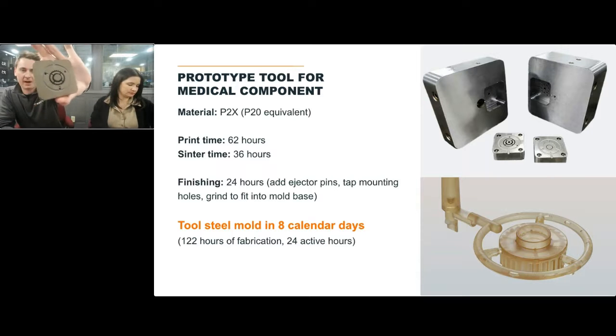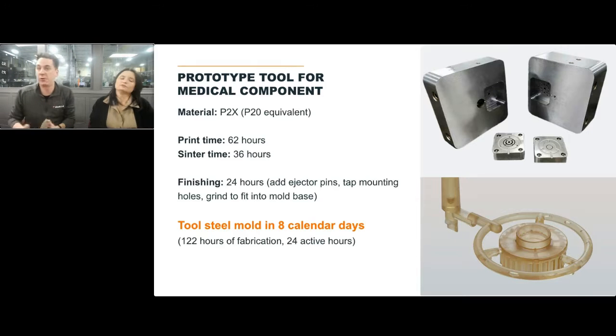So about 122 hours of total fabrication, which they did in just 8 days, of which only 24 hours were active. We're hearing a lot these days about labor and the challenges of hiring toolmakers, and the ability to do just 24 hours of tool making time instead of hundreds of hours is obviously really, really beneficial in these applications.